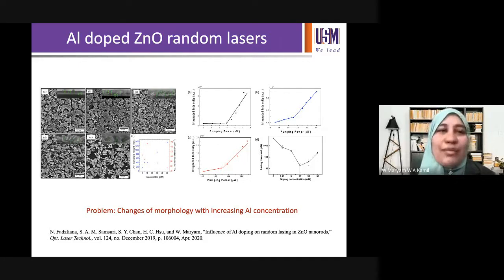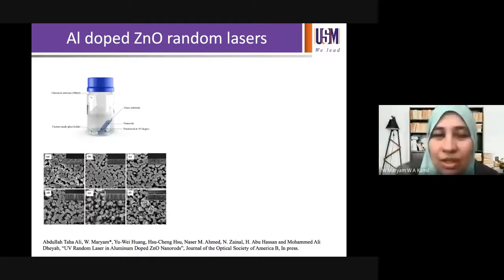So what we did was, we have already tried doping. Can we actually do doping without changing the morphology much? This paper is in press. It was just accepted last week, so it's not published yet. But I would just share with you what we've done. My student here, Abdullah, tried to create nanorods using a semi-autoclave kind of method. He found out that with this method, you can get roughly the same size, up to E. There are not many changes in the diameter of the rods.